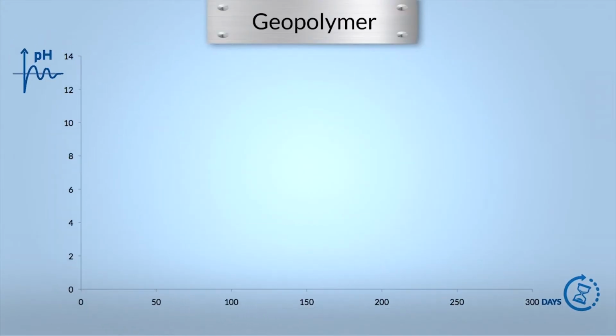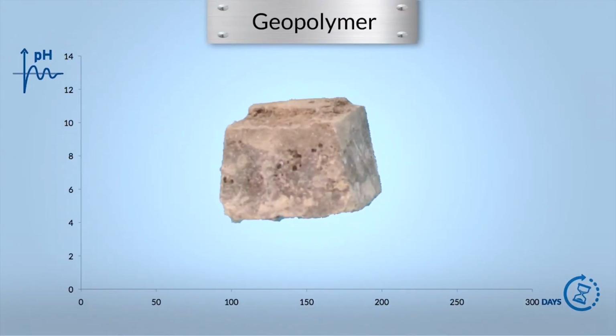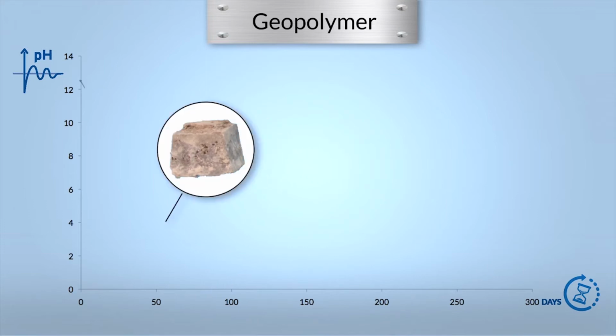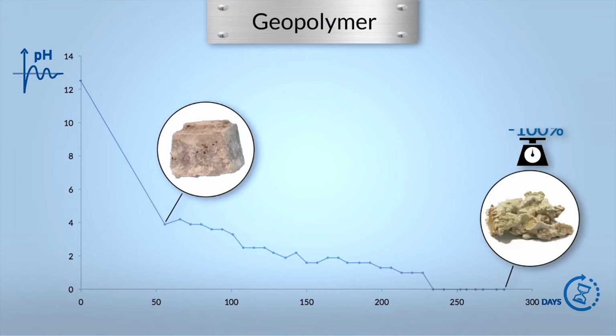This third set of specimens are made with a so-called geopolymer. Although the manufacturer claims this product is acid-resistant and thus adapted to corrosive sewers, it did not survive the action of bacteria. The surface pH decreased to 0 within 8 months, and the material turned to a muddy texture to the point that the weight loss after 9 months is 100%.